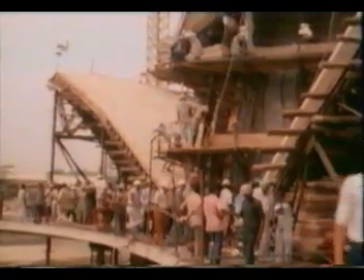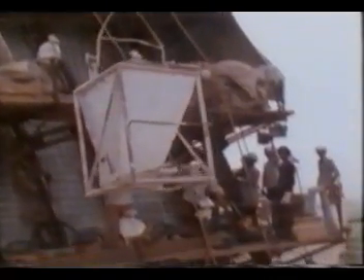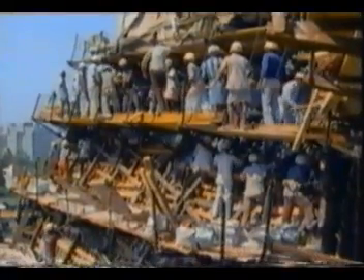As concreting commenced, the outer formwork was put in position 1 row at a time. To compact the concrete, needle vibrators were threaded into pre-planned positions by workers standing on platforms 10 meters above the pouring level. As soon as the concrete reached the level of the outer formwork, the masons and concrete teams stepped back, and the carpenters rushed forward to fix the next level of the outer formwork. They had only 10 minutes to complete the task, lest the concrete begin to set. A supervisory team then quickly double-checked the reinforcement and forms placement, and the next level of pouring immediately began, repeating the entire cycle, step by step.